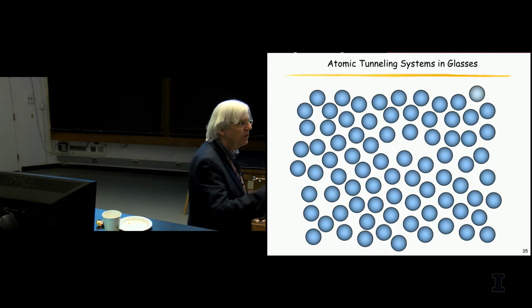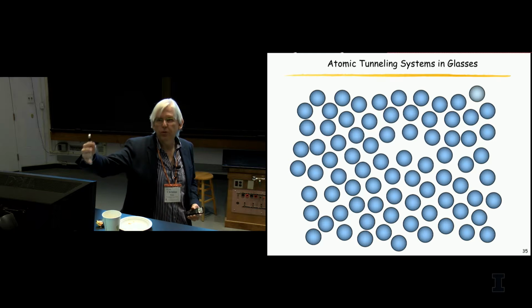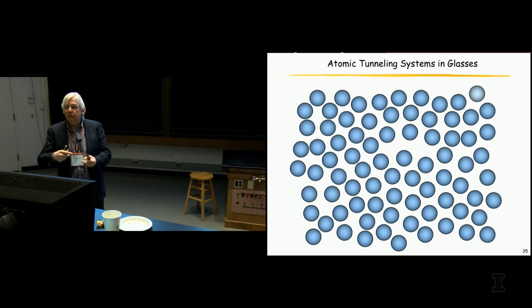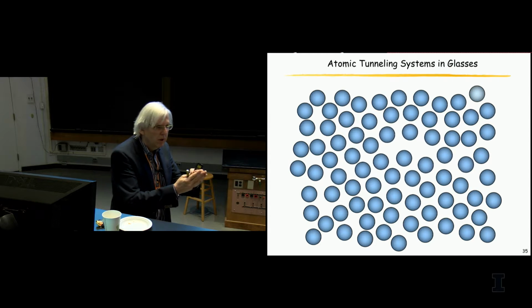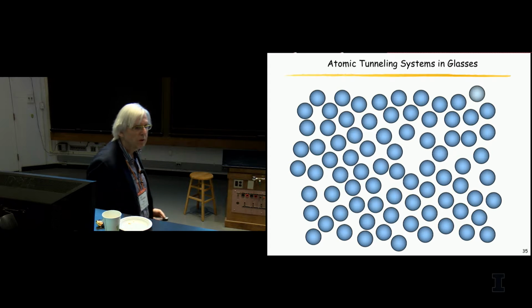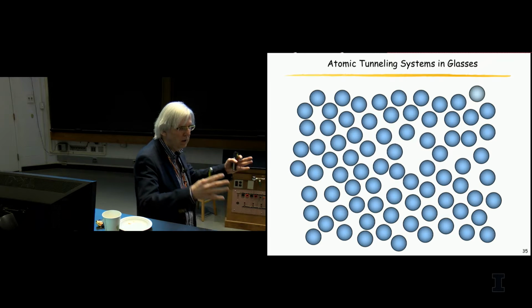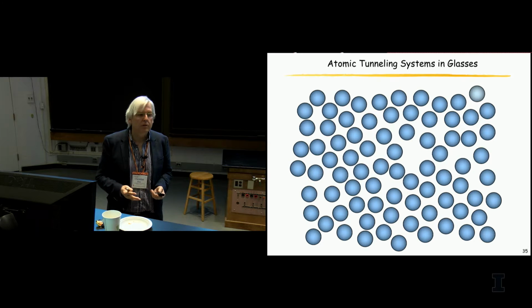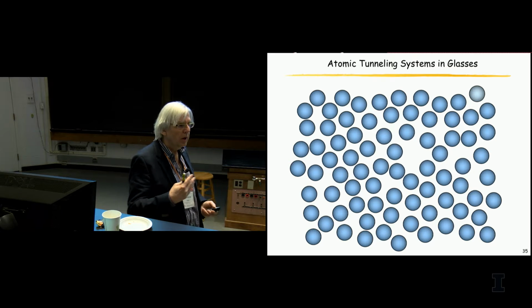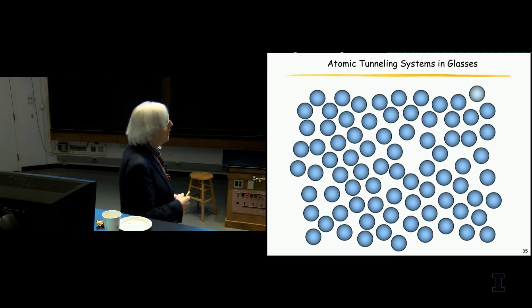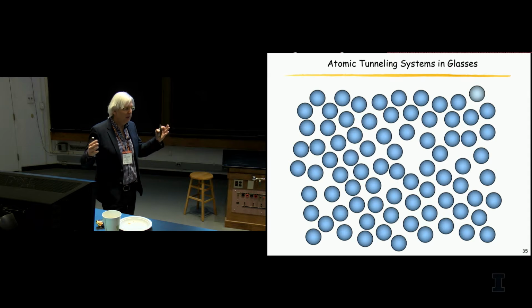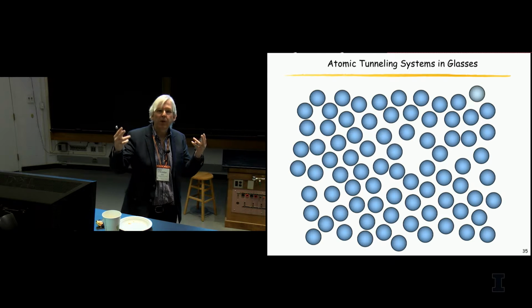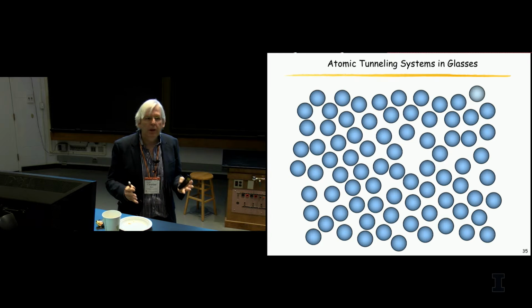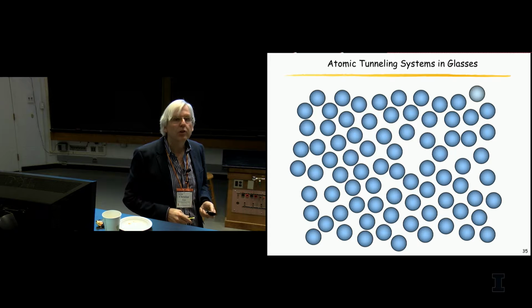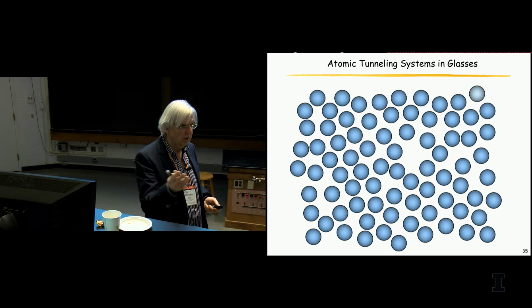And if it moves, it changes the field gradient. The field gradients of those atoms are changing. And since the field gradient talks to the quadrupole moment, the tunneling system can talk to all the quadrupole moments in the surrounding, and energy can be transferred. So that's the local bath. If you do numbers, about 1 million nuclei in the surrounding are seen by a typical two-level system. And if you drive the system hard, we did that, you can also saturate that bath. But I do believe this is the right explanation. And since the number of two-level systems, the number of spins is not changing, and also not the coupling mechanism, there's no temperature involved. This mechanism has a constant relaxation rate. And therefore, we have this constant position of the minimum.